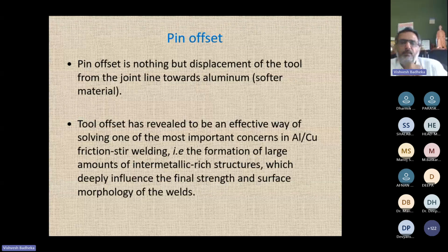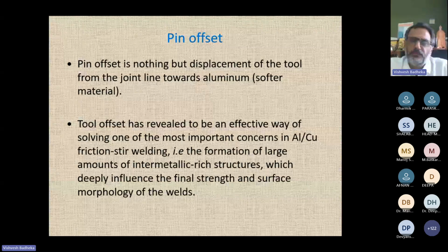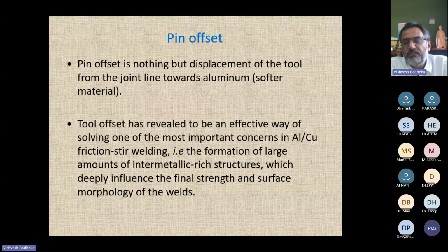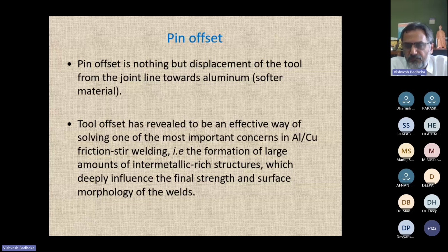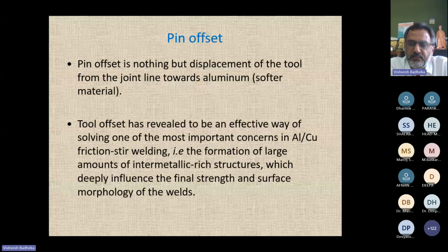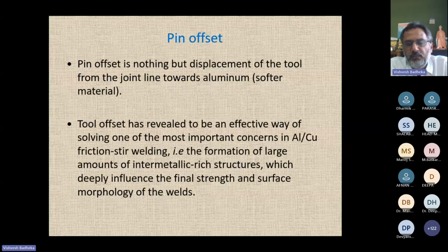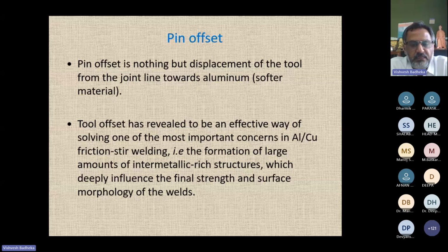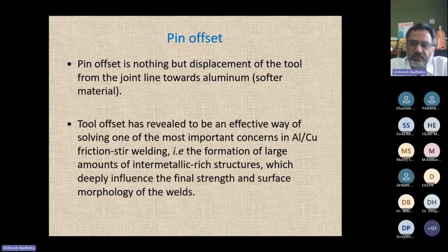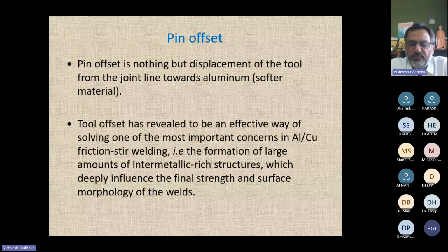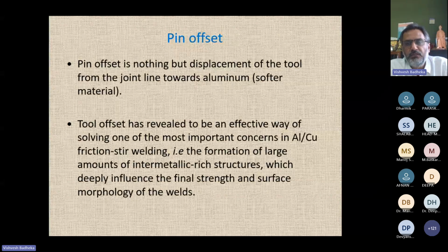The pin offset is nothing but a displacement of the tool from the joint line towards the softer material. And the offset has proved to be an effective way of solving the most important concern in dissimilar welding, I mean aluminum copper dissimilar welding, which is the formation of large intermetallic structures. If you put it exactly in the center, you may get a lot of intermetallics, and then properties like strength, toughness, ductility will be affected. But if you put the pin more on the softer side, it will help you to reduce the intermetallic formation and it will also help you to improve the joint property.